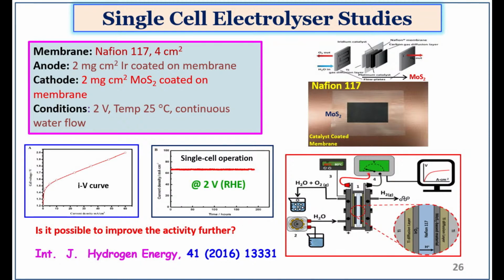And then the conditions are that we polarize at 2 volt at 25 degrees, and you allow continuous water flow, because as I said earlier, it's a complete system. You allow the water inside, you have the Nafion membrane, an acidified membrane, so that you can apply the potential and then get the hydrogen gas at the cathode and oxygen gas at the anode.